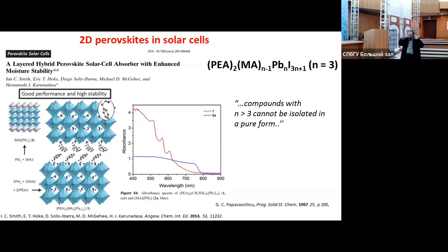And one thing that struck me, and this is how I started looking into this system, is that whereas for the three-dimensional perovskite, for the bulk of the perovskite, we have a very nice clean absorption. In the case of these materials, when you synthesize the crystal, dissolve in a solution, and try to make a film for a solar cell, you see a picture that looks like this. Steps. This cannot be a clean material, obviously. This corresponds probably to discrete absorption coming from discrete materials.